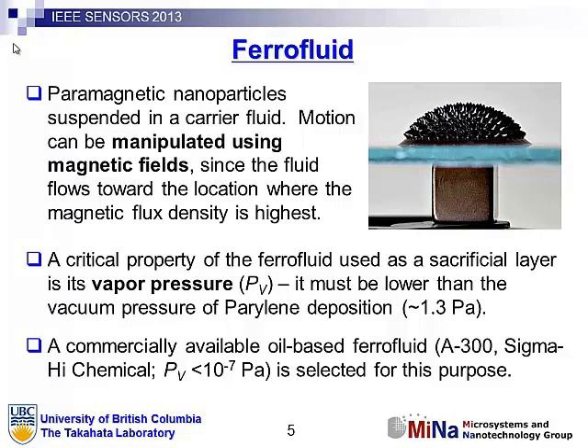So in our particular fabrication process, we needed a ferrofluid sacrificial layer that would survive inside a vacuum, as we do processes in the vacuum, in particular inside a chemical vapor deposition of Parylene, which occurs at 1.3 pascals. So we chose a ferrofluid indicated at the bottom there with a very low vapor pressure, which is not affected by a vacuum environment.